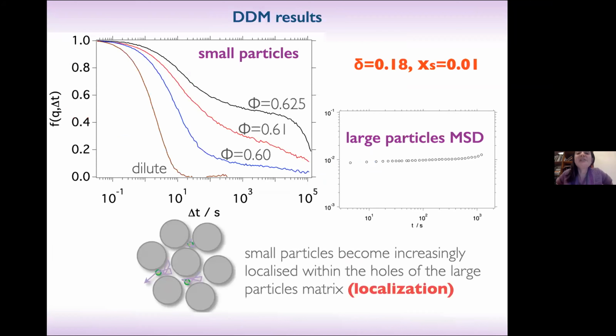And so the interesting results of the differential dynamic microscopy of Marco and co-workers were the following. At low size ratio, 0.2, in this modified Lorentz gas limit, what happens is that the density correlator goes to 0 when the large particle packing fraction is around 0.54, let's say. You increase the packing fraction of the large particles.